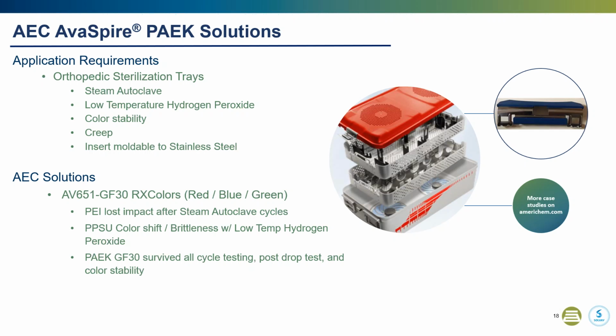We identified a couple solutions in different polymers and different fillers with what we call our shotgun approach. We completed the color matches and the 55-pound samples in each variation within 2 weeks. It was found that our glass-filled polyetherimide formulations lost impact after autoclaving, and our Radel samples had some color shifts, some embrittlement issues after the low temperature hydrogen peroxide protocol. The AvaSpire formulation with AV651 with our 30% glass stood up to both in regards to color and strength.